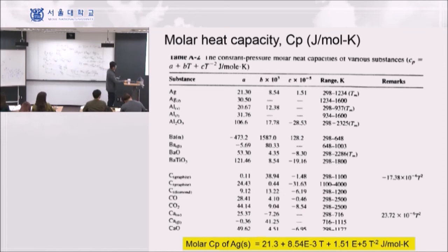And then if you go down now, you can see graphite. What's this value? I want to express most of this table, most of this heat capacity, as A plus BT plus CT to the minus 2. However, for graphite, we cannot express the heat capacity by using only three constant values here. So we have to add an additional temperature dependence term. That's the additional term here.